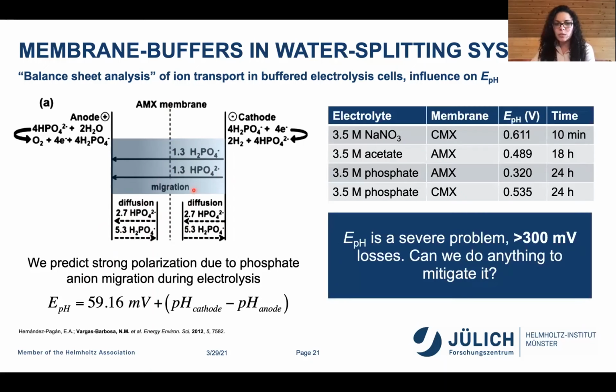So what we did is we ran electrolysis, and then we measured the pH of the cathode and anode after different time points, and then we used the Nernst equation to calculate the potential losses due to the pH. And what we observed is that in completely unbuffered systems, this polarization is extremely high. Already 600 millivolts in about 10 minutes, and this is all at, I apologize for the missing data, 25 milliamps per centimeter squared.